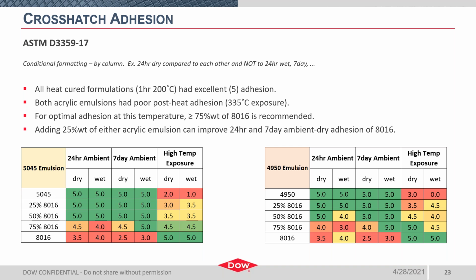It is confirmed here that both acrylics do have excellent adhesion to cold rolled steel after 24 hours and 7-day ambient dry. Where they're going to need a boost in performance is in that post-heat adhesion. This was very low or even non-existent in the case of 4950. And this is where we see that silicone inclusion linearly improved the high temperature resistance. As you add more 8016, you increase the dry and wet post-heat adhesion. Of course, the silicone binder on its own, shown in that last row on either table, does exhibit the best post-heat adhesion. My first hybrid study echoes what I've said now many times throughout this webinar. This set of silicone acrylic performance data enables us to make better recommendations on starting point formulation depending on the individual application requirements.